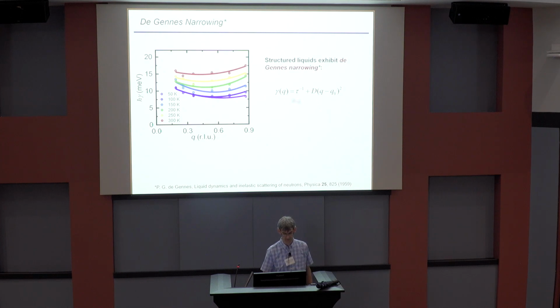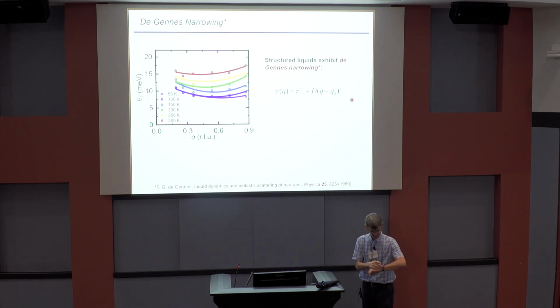meaning it fits this form. And those of you who've done neutron scattering may know that DeGennes wrote a paper in the 1950s on neutron scattering from structured liquids, and what he showed is that they exhibit what we now call DeGennes narrowing, which is a minimum at a wave vector that's dependent on what objects are fluctuating. And let me just explain that for a minute, since I have been disciplined and not wasted too much time.